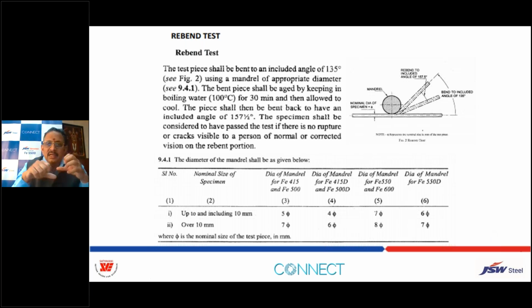we actually in the site, we fabricate the reinforcement, assemble it at the site, and at the site we require some change and we do the rebending. So there is a gap between the bending and rebending. So in the test also, it is recommended to give the time lapse between the bend and rebend when we are testing, so that it represents the realistic site condition. And if you are satisfied with the quality of the reinforcement rebar, so we can use it.